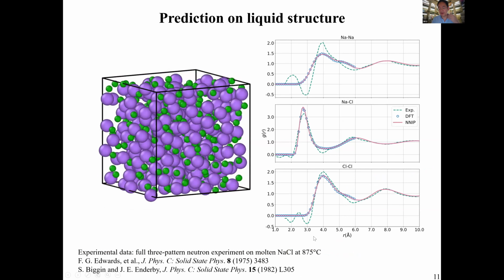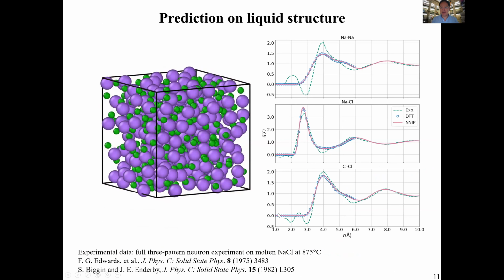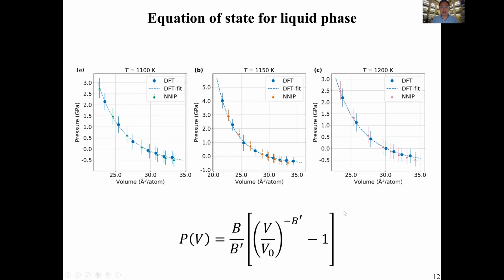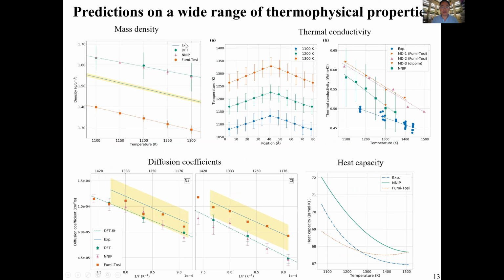And then we use it to do, for example, high temperature molten salt. When we compared with neutron scattering measured radial distribution functions, we were told that some of these differences are actually experimental artifacts. The experimentalists told us this is actually pretty good agreement. We fit the equation of state for the liquid phase. We can fit things like thermal conductivity, mass diffusivity, heat capacity. I just want to say that our goal is not to reproduce the experiment, because DFT itself has some error. Our goal is really to show we can reproduce the DFT data.